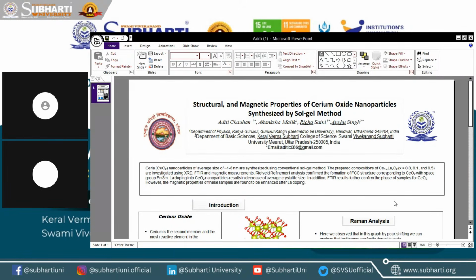The abstract of my poster presentation is: Ceria nanoparticles of average size 4 to 6 nanometers are synthesized using the conventional sol-gel method. The prepared compositions of cerium-lanthanum oxide are investigated using XRD, FTIR, and magnetic measurements.